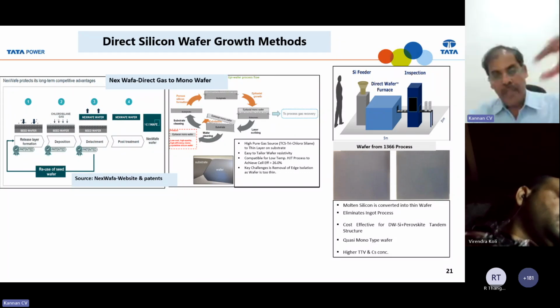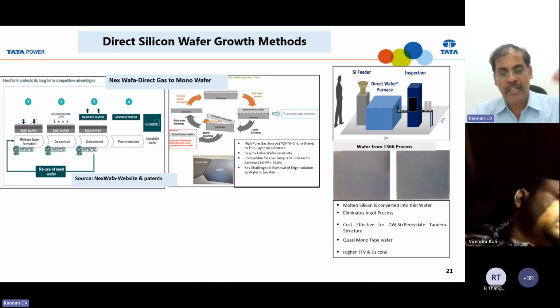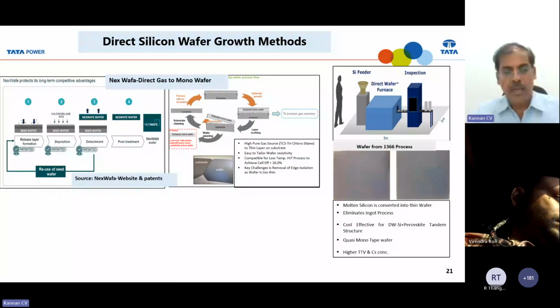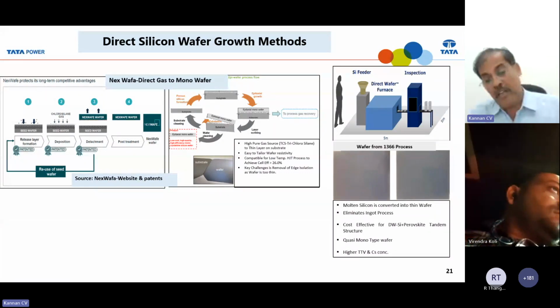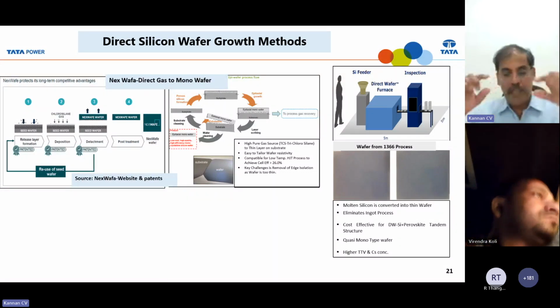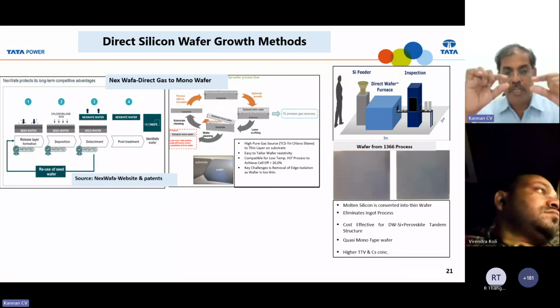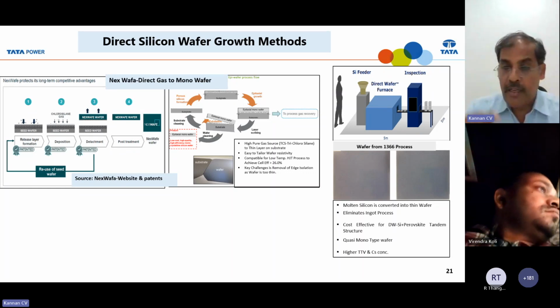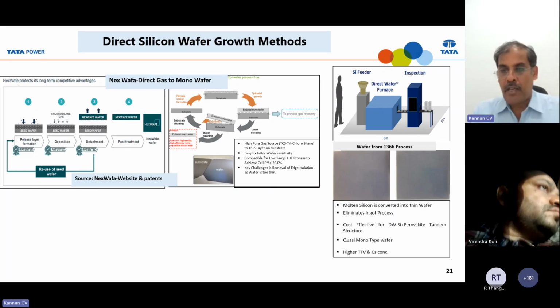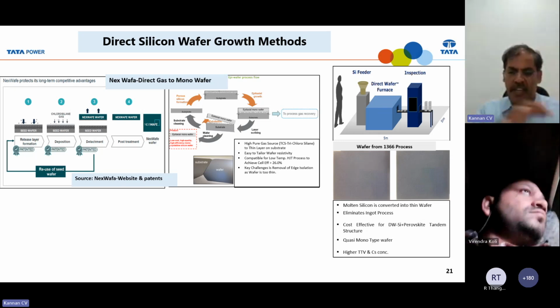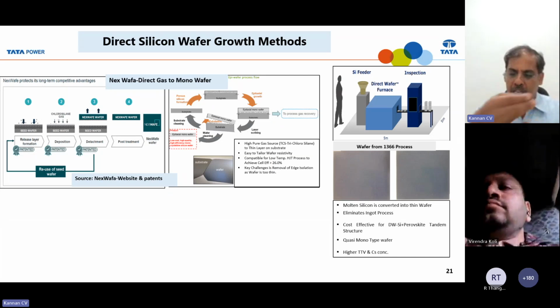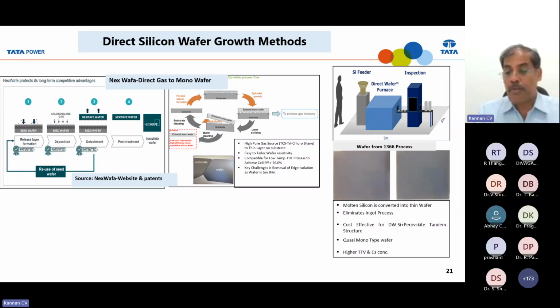And here, using the gaseous, different gases, silane, trichlorosilane, you dissociate silane into silicon and H2, then deposit that silicon onto a different substrate, and after certain time you can take out that thin substrate and use it for further processes. And another technique is 1366, a company where instead of converting into square shape but cylindrical, directly melt it, directly pour into the substrate, then take out the wafer. But unfortunately, it's a multicrystalline format. You cannot use it for high efficiency technology. So every technology has its own pros and cons, but these are the broad level of different types of technologies available in the market.